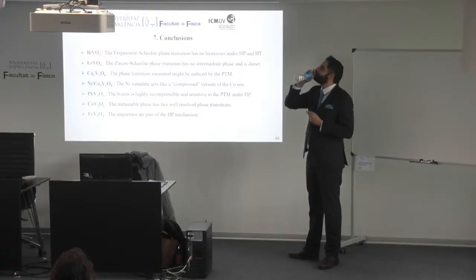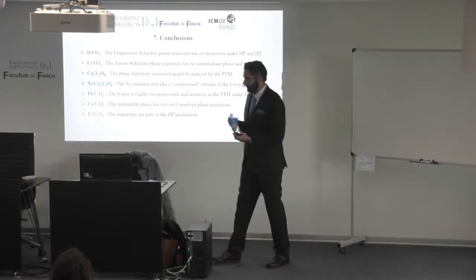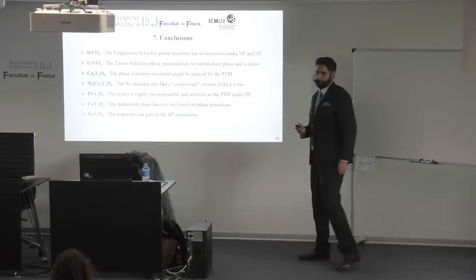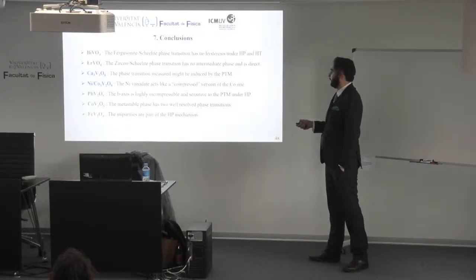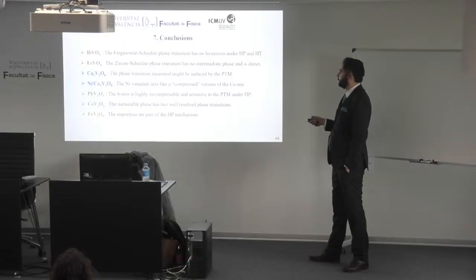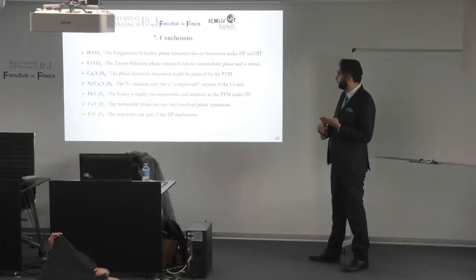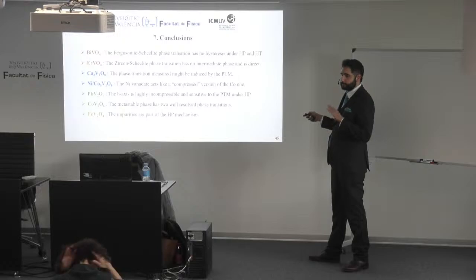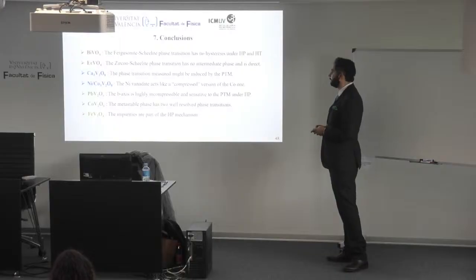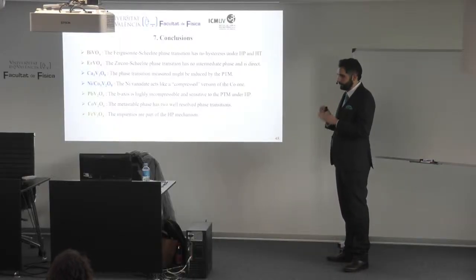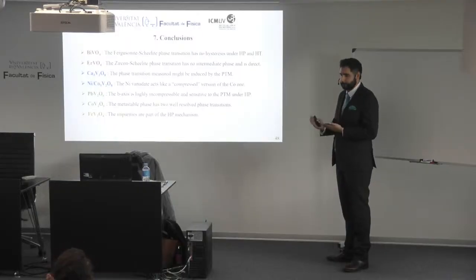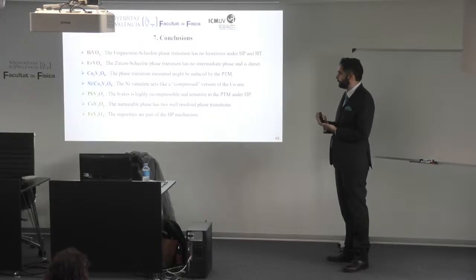Going to stop a bit. I'm going to highlight one conclusion for each sample or for each work. Okay, so for the bismuth vanadate, we saw the second order ferroelastic phase transition in pressure, temperature, and combining both of them, and confirm that it has no hysteresis in this range. For the erbium vanadate, we confirm that there is no intermediate phase in between this phase transition, and indeed is direct.